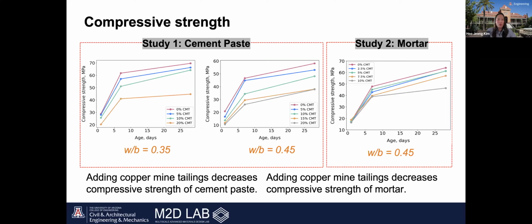And the test result for mixtures with different amounts of copper mine tailings shows that the compressive strength decreases as both the water to binder ratio and the CMT percentage increase. And a sharp increase in strength is observed during the early curing period from 1 day to 7 days. And after that, from 7 to 28 days, the rate of strength gain becomes slower. However, the cement paste with the CMT never reaches a higher compressive strength than the control mix without CMT. Even so, all specimens at 28 days still meet the minimum strength requirement for structural walls, which is 20.68 megapascal or 3000 psi.